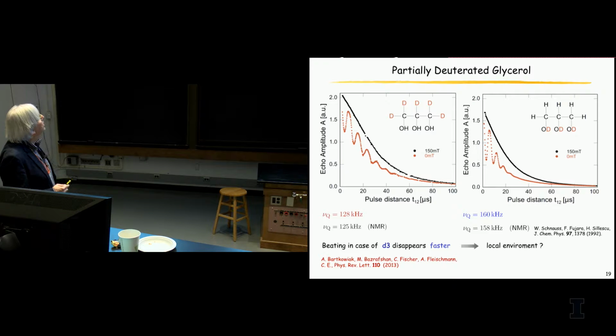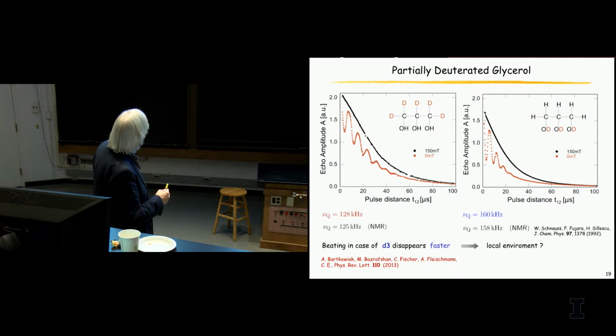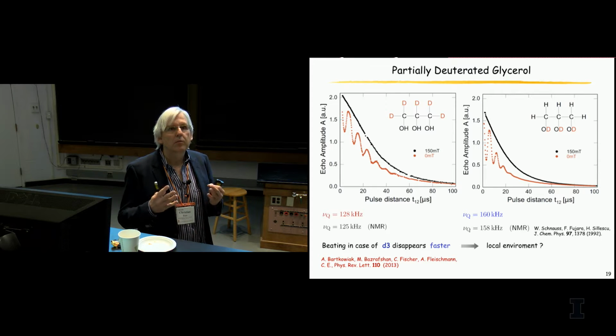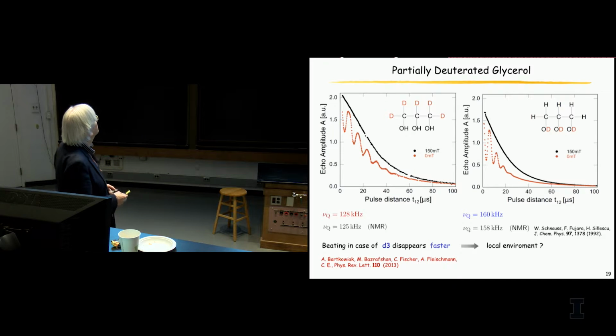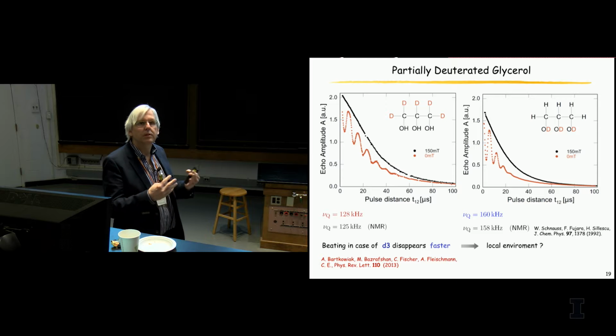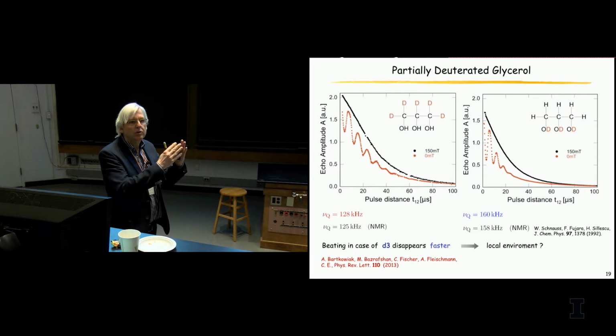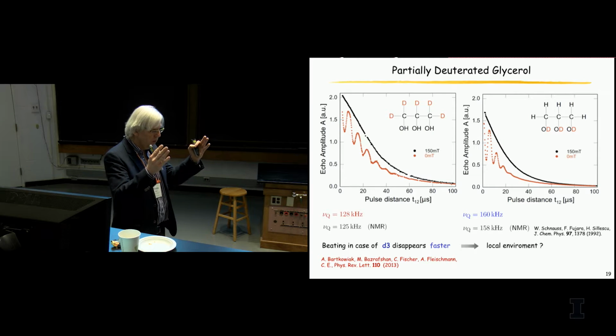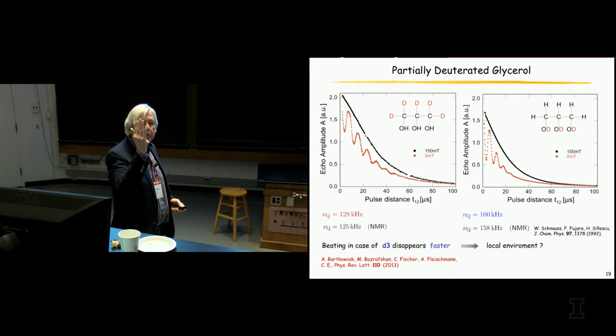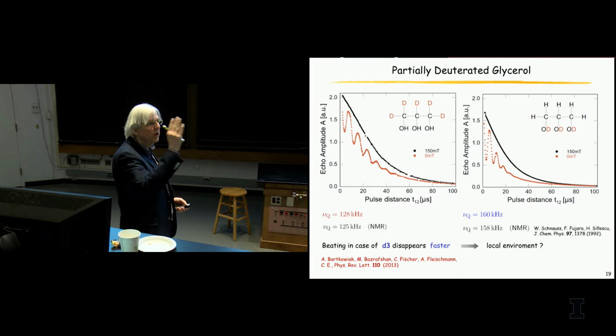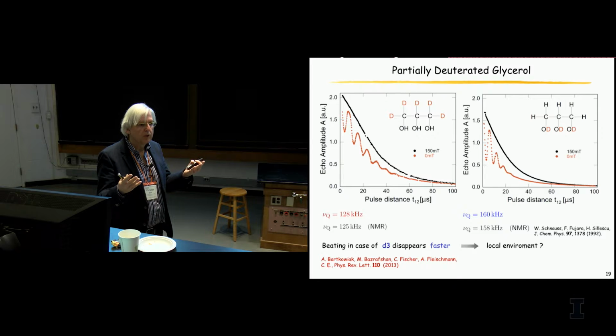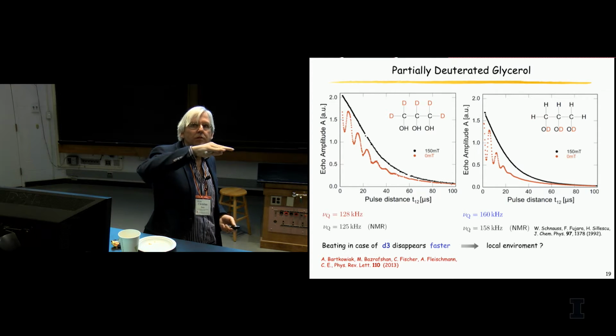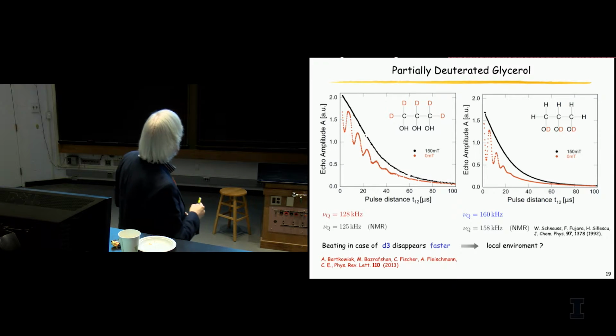And this is here now in partially deuterated glycerol. You see here only the 5 hydrogens replaced by deuterons which are bonded to the carbon. And you see here very nicely in zero magnetic field these huge oscillations. And when you look at it, actually they have the right frequency, something you can determine at room temperature also with NMR experiments. When you go to large magnetic fields, what happens is it subsides. And that's clear too, because if you have a large magnetic field across your double well potential, then in both potential wells, the quantization axis for the nuclear spin is given by the magnetic field. So they cannot distinguish left and right anymore, and there's no coupling to the two levels anymore. So in some sense, in whatever nuclear state the system is, it will look like a two-level system. That's exactly what you see here.